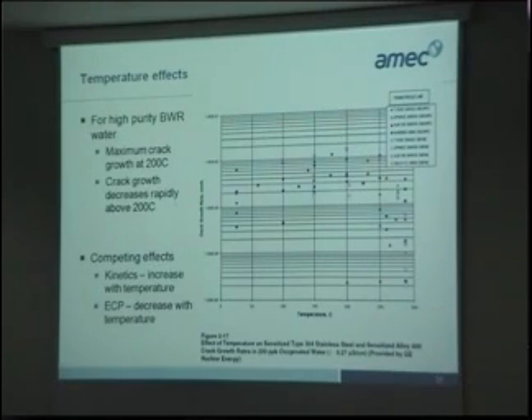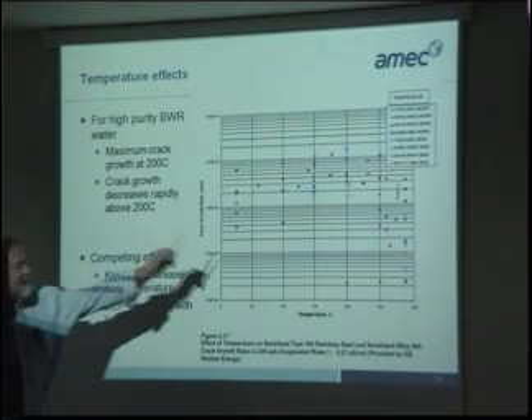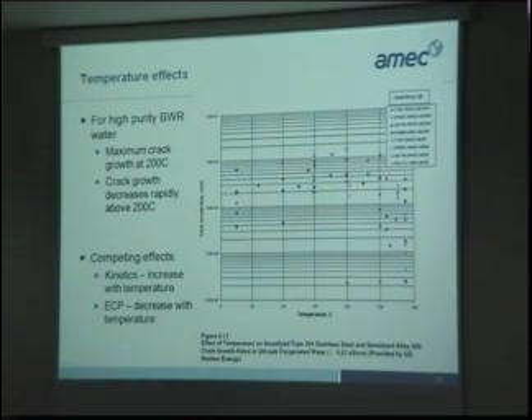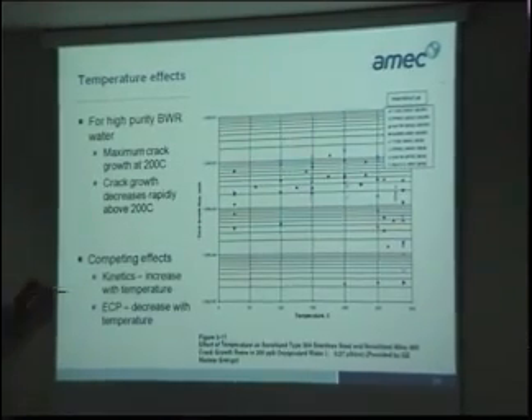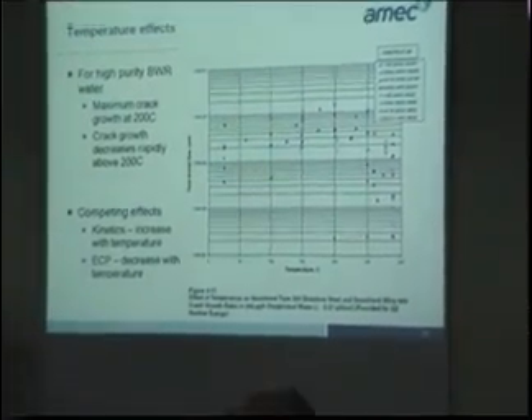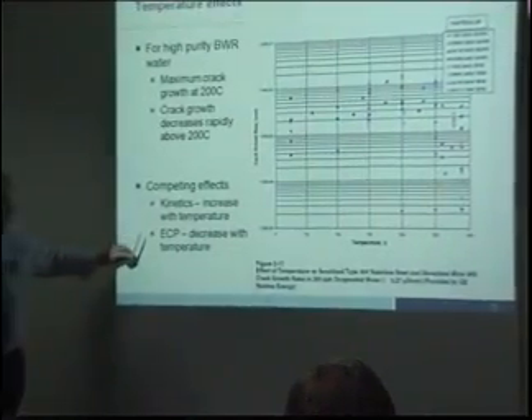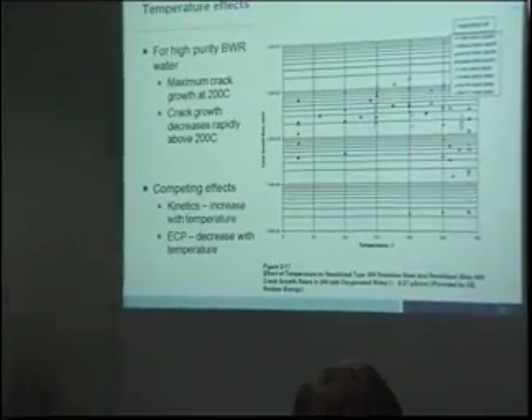Temperature effects. I know this looks a bit like a sky at night, but there is a sort of slight correlation there. And for high purity water, we found a maximum crack growth at about 200 centigrade, and the crack growth decreases rapidly above 200. But there's two competing effects here. There's a kinetic effect, which gives you an increase with temperature, but the electrochemical potential decreases with temperature.